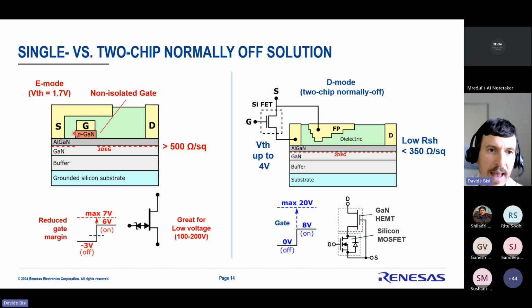It's a very well calibrated technology, so magnesium doping is not an issue. They found the right processing sequences to activate the magnesium to get the right threshold. On the fabrication side, I think everything is under control. If I had to point out a few challenges that are not a big issue for low voltage, but can be a problem for high voltage, it is that the gate is not isolated. At the beginning there was a technology called GIT, with an ohmic connection between the gate and the p-GaN. But that connection was very leaky. When you turn on the device, there was significant gate current, which is very delicate and maybe not suitable for high voltages.